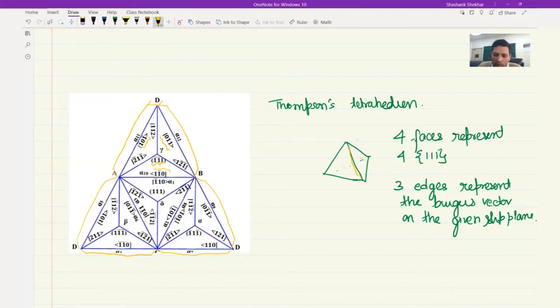For example, a/2 [1, 1bar, 0] lies on (bar1, bar1, 1) but also on (1, 1, 1). Therefore, the dot product of this vector with each of those plane normals is zero. So if someone asks you to solve an example where cross slip is taking place in an FCC system and you need to identify the two possible planes, you can clearly identify them using Thompson's tetrahedron.